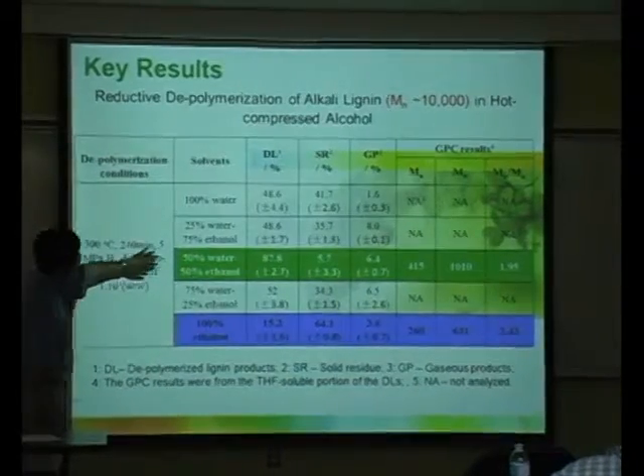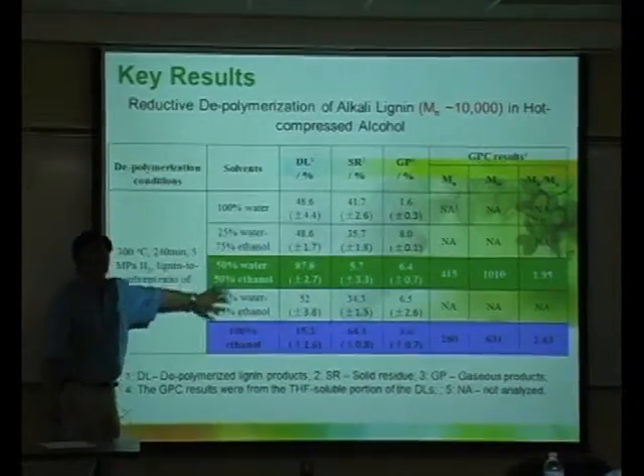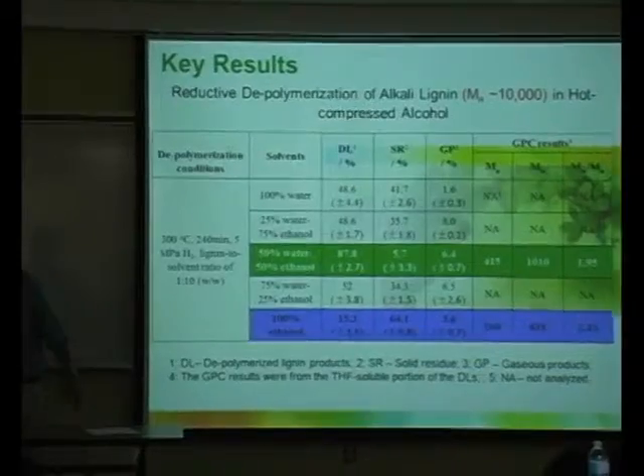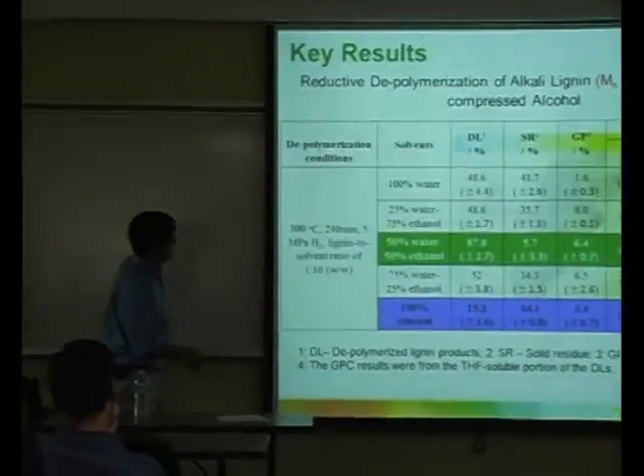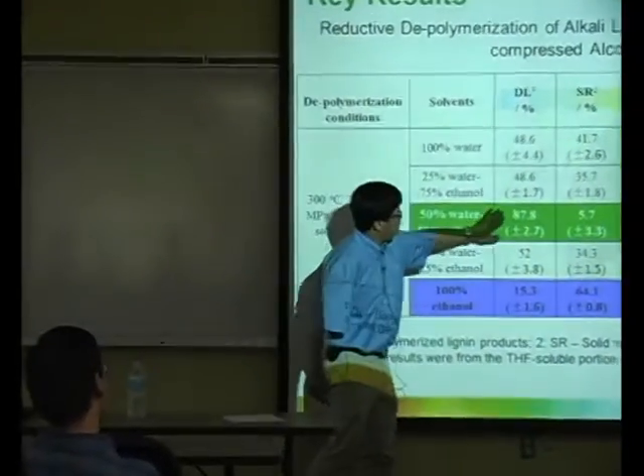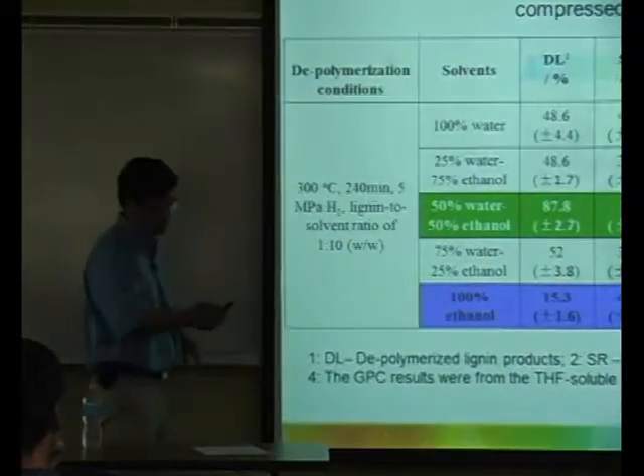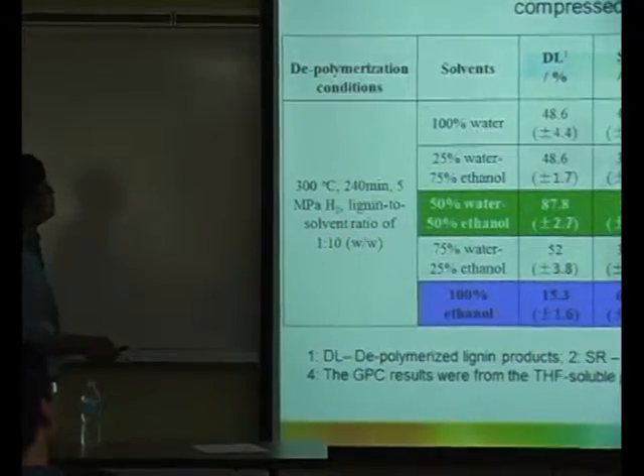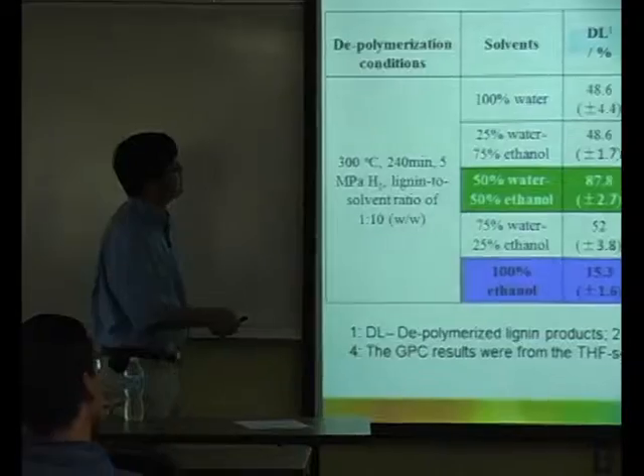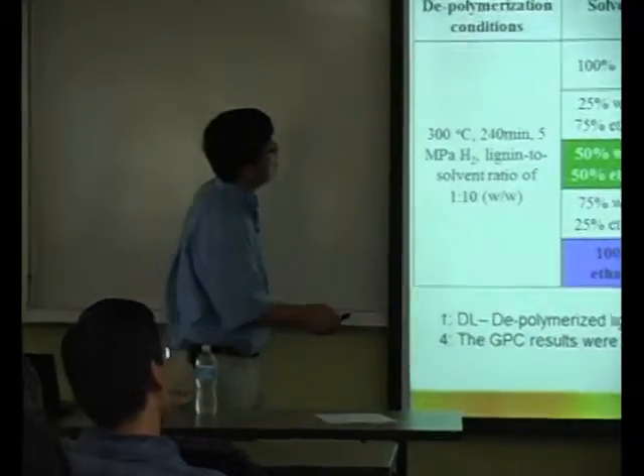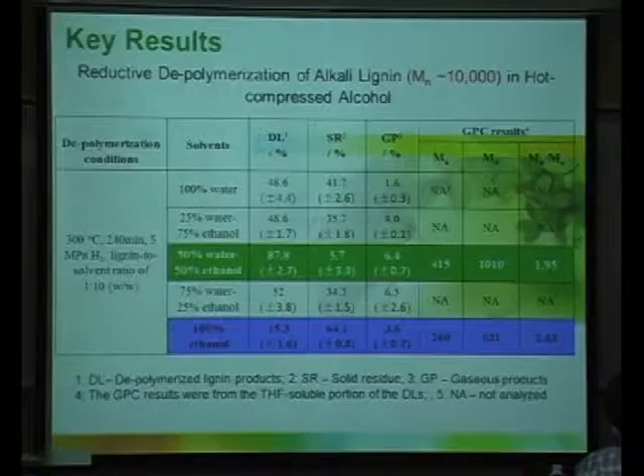But compared to this system, the water-ethanol co-solvent system, we can look at the difference. So almost double the yield. The yields are close to 90%, very high yield. And then the GPC result. GPC is gel permeation chromatography, for the molecular weight determination. So we can determine the molecular weight, Mn.